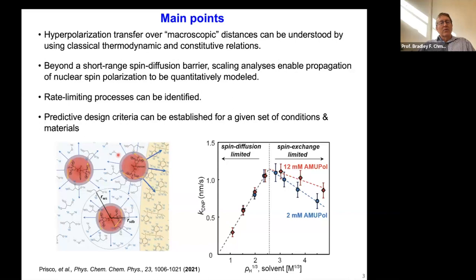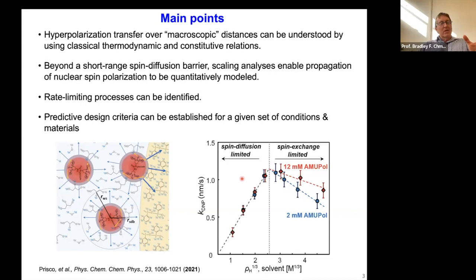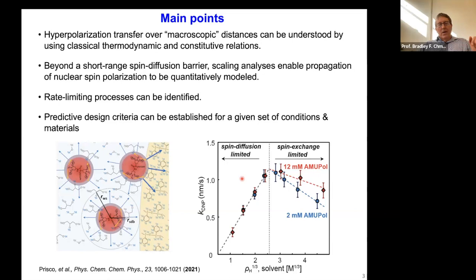What's different about material science applications of DNP is that if we're talking about a cement particle or a polymer, there's a dissimilar interface. On the left, you have a collection of bi-radicals in a frozen solvent against a polystyrene sphere. The polystyrene sphere is highly protonated, while the solvent is partially deuterated for reasons that will become clear. We're going to show there are certain regimes that are spin-diffusion limited and others that are spin-exchange limited, depending on variables we can identify analytically without adjustable parameters.